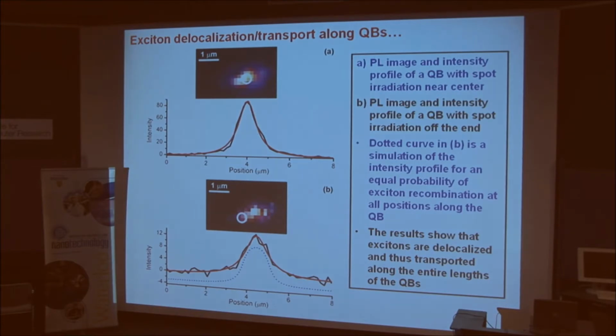Okay, well, we did an interesting experiment. Rich's group, Ginny and Rich, did an interesting experiment to establish that the excitons are in fact delocalized along the entire lengths of the belt. And so this is what they did. They irradiated a belt with a small spot size right in the middle of the belt. And then they measured the intensity profile along the length of the belt. And this is the emission intensity profile along the length of the belt. And so the maximum emission intensity is right in the middle. Well, you might say that's not so surprising because, in fact, that's right where the belt's being irradiated.